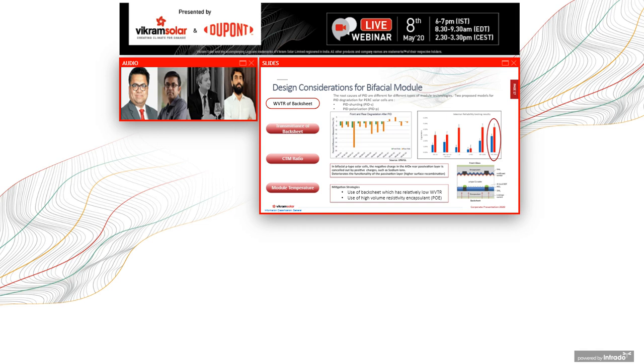Now, because of high moisture ingress through the backsheet, the mobile ions of sodium, which are principally responsible for PID, actually can deteriorate the rear faster. And this is what we also see in the graph on the right-hand side. This is our internal reliability testing data, where the rear side fails. The failure rate of the rear side is higher after 96 hours than the front. So therefore, this rear failure is always something which you need to consider, and WVTR is an important parameter as a result of that.